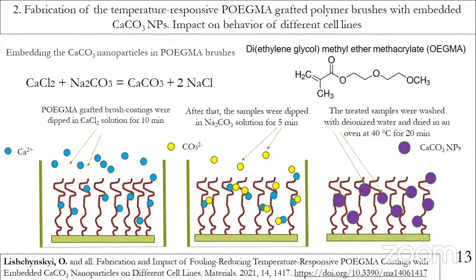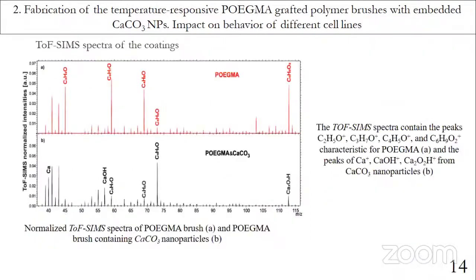Next project is this combination of polymer brushes with nanoparticles, such as uniform calcium carbonate nanoparticles embedded in polymer grafted brush coatings, which were synthesized using precipitation from solution of calcium chloride and sodium carbonate. The ToF-SIMS spectra contain the peaks characteristic for polymer and the peaks from calcium carbonate nanoparticles.